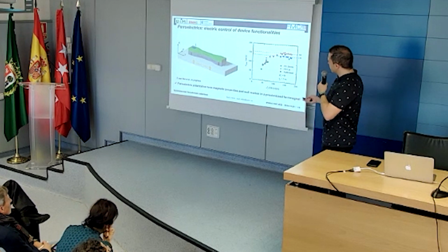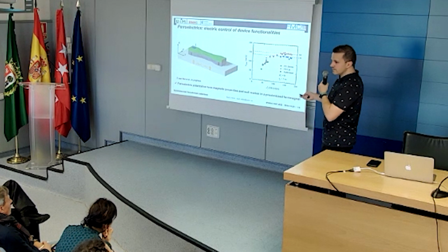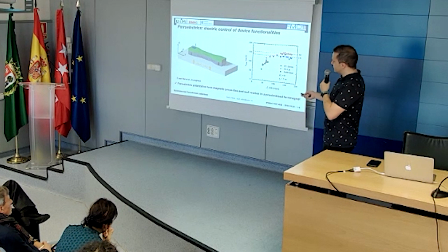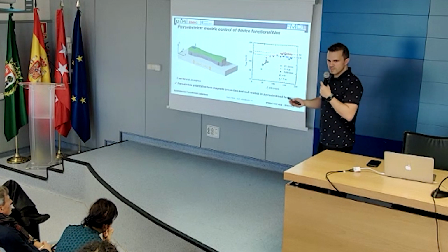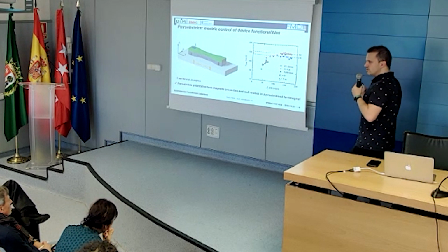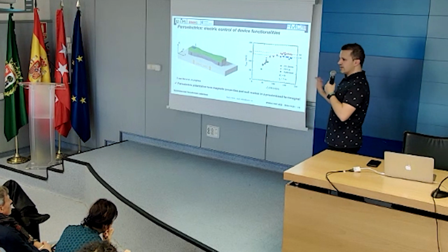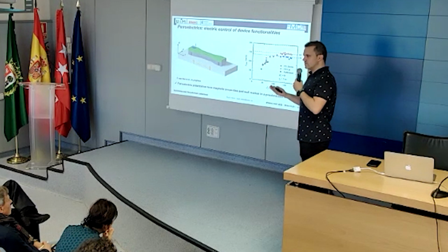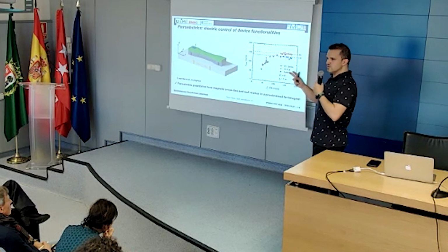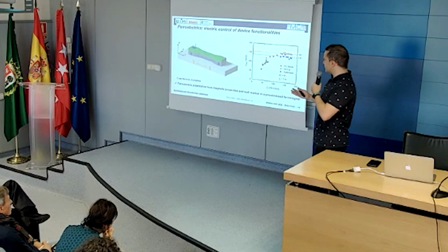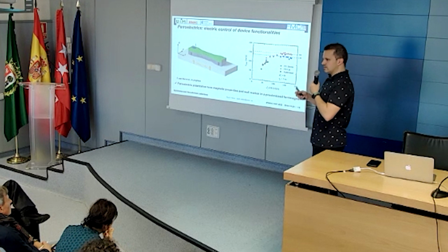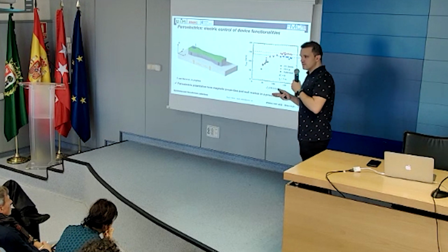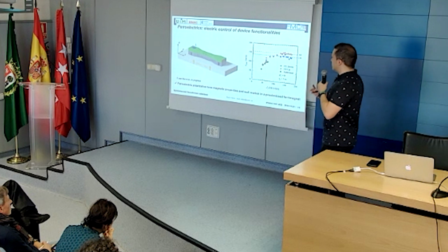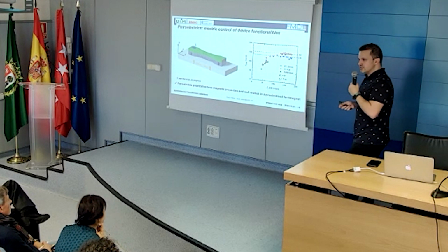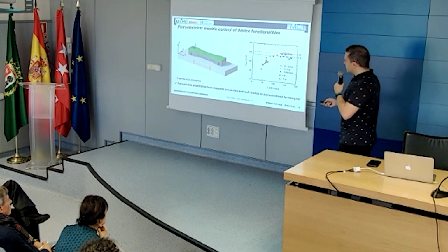And now what you think about is what's happening at the interface. The interface feels some local electric field, and this is equivalent to shifting properties by electric fields. It's known in the literature that you apply a static electric field to a magnetic system and you change properties of the magnetic layer, like stabilization of chiral domain walls or the spin conversion phenomenon, for instance, at the interface. And that's what we want to do.